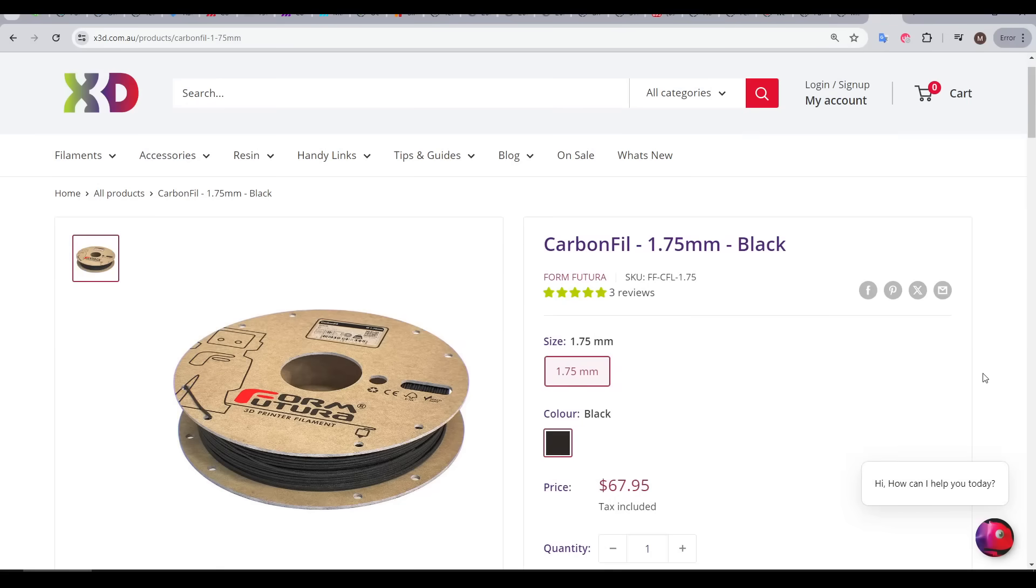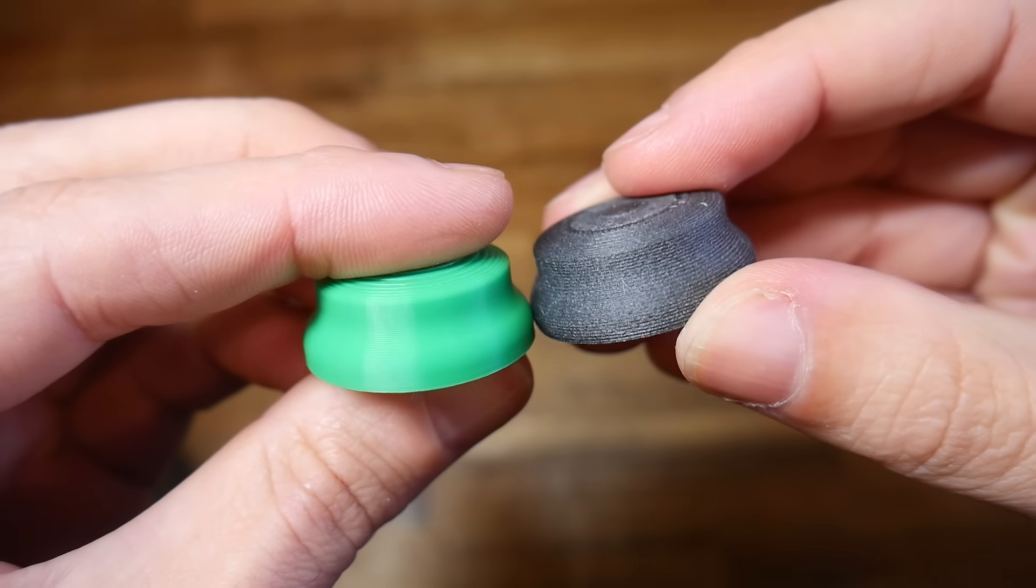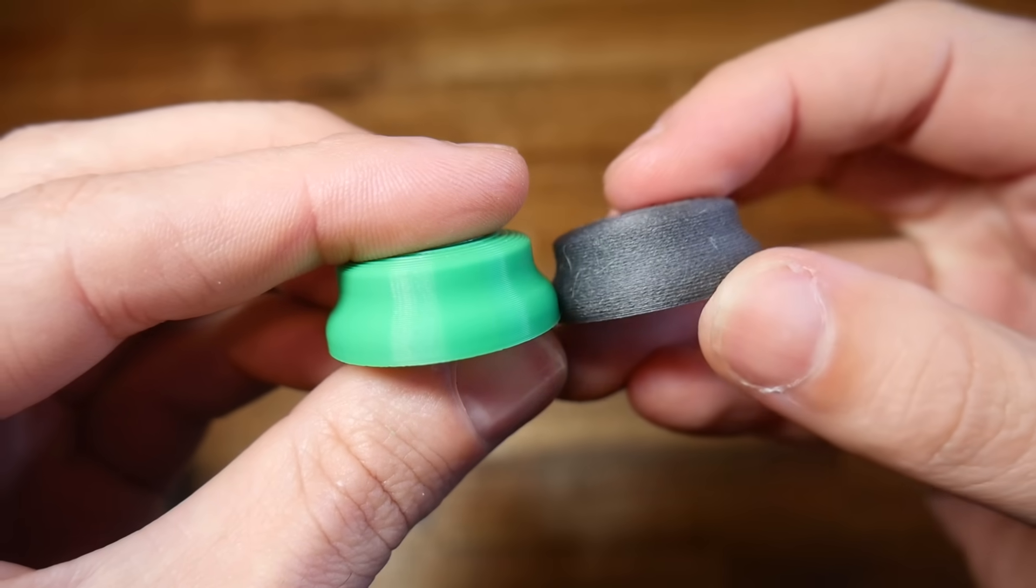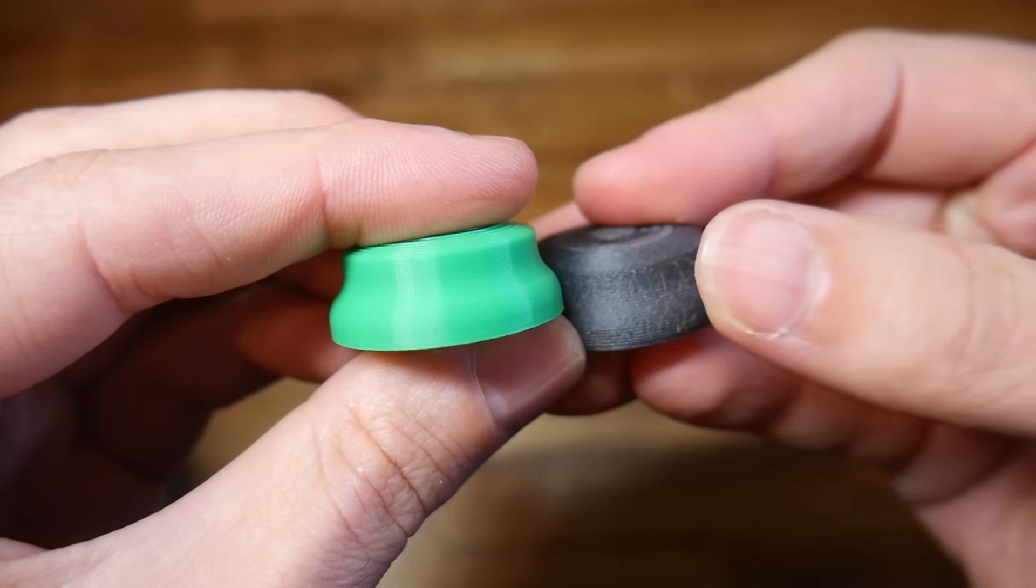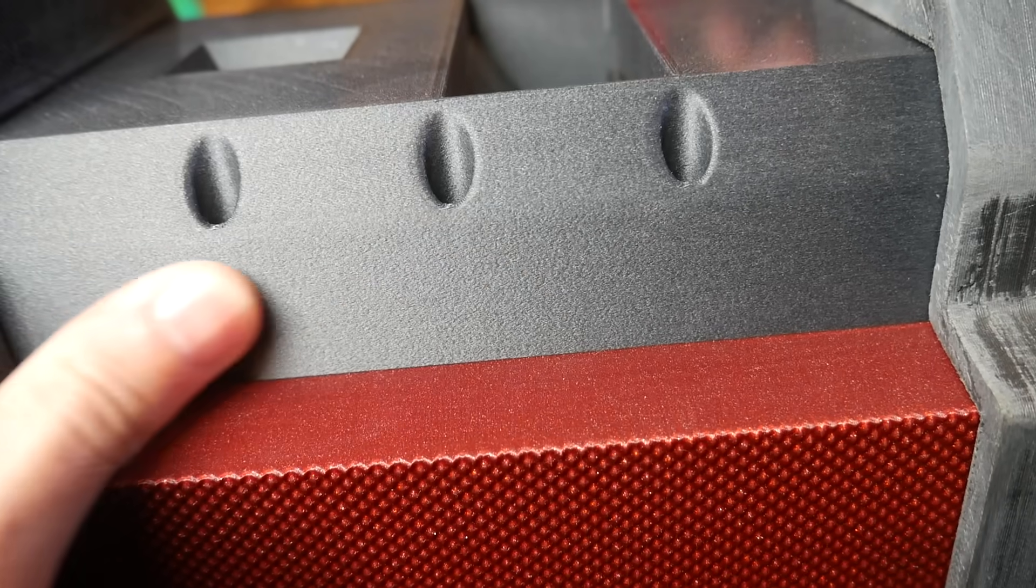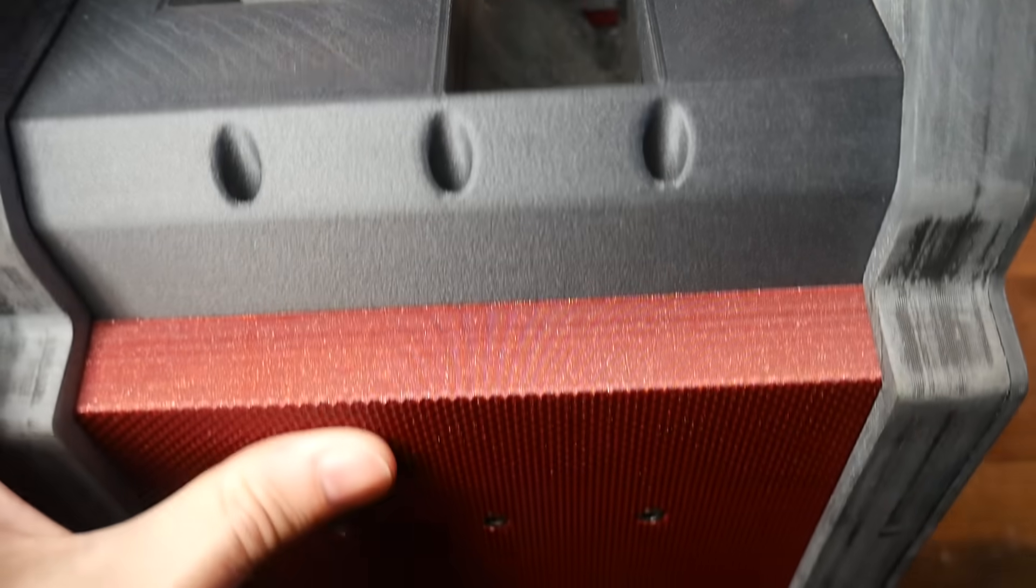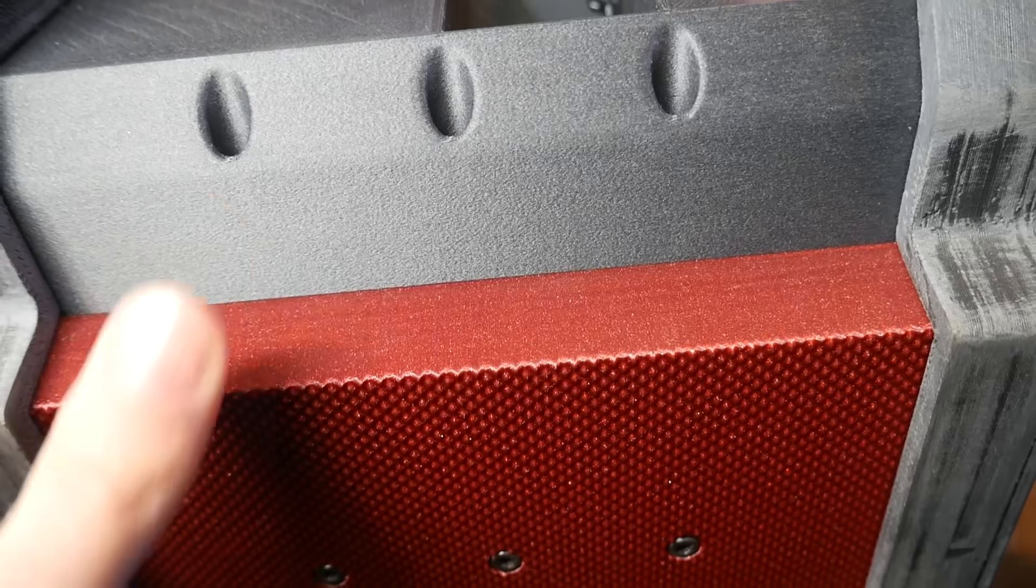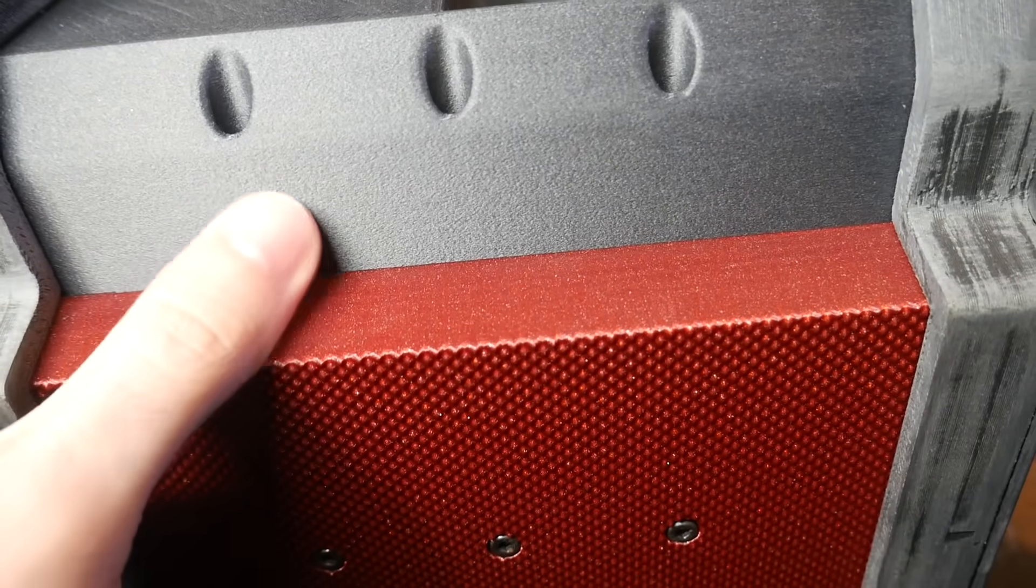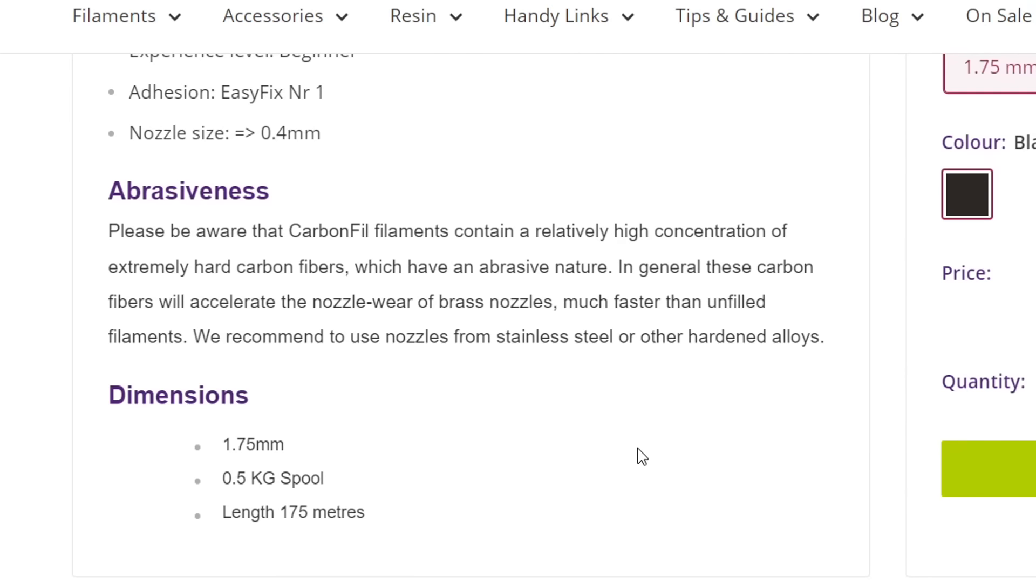You can get a similar effect with a composite filament for instance one filled with carbon fiber particles. In this case if we compare our baseline to the carbon filled filament it's actually pretty disappointing. Texture has been added but the texture is so rough that it's catching the light and probably making the layer lines stand out more. Nonetheless I'm leaving it in this guide video because in the past I've had great success with carbon filled filament. Here we can see carbon filled nylon next to some metallic fleck PLA and the end result is something that doesn't really look 3D printed on most of the surfaces at least. Just remember that with composite filaments those carbon fibers are abrasive and you need to print them with a hardened nozzle to avoid premature wear.